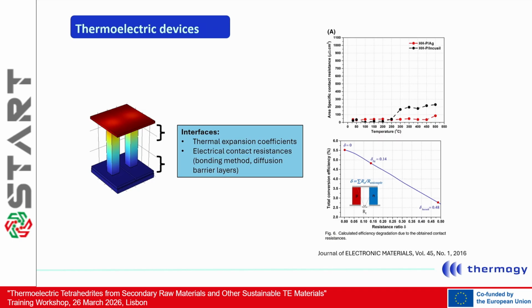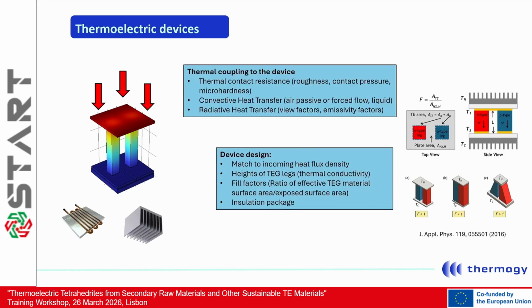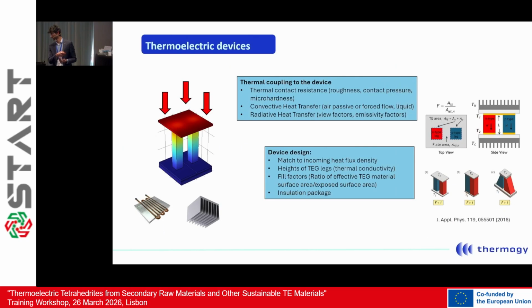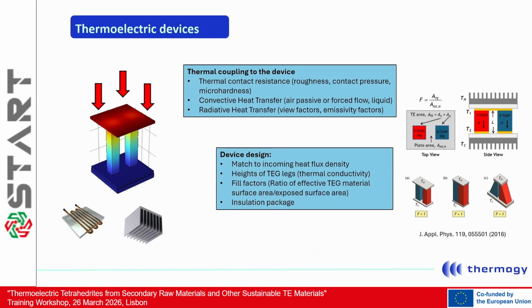So from the unicouple, now when we go to the device, zooming out, what you see is: how do you get the heat in and the heat out? So that's where the thermal coupling to the device itself starts to play a big role. Depending on what kind of application you have, a conductive heat transfer, a convective, or a radiative, each one of them has its own characteristics. So in the contact resistance, the roughness of the surfaces starts playing a big role here. You want the heat transfer coefficient to be as high as possible.